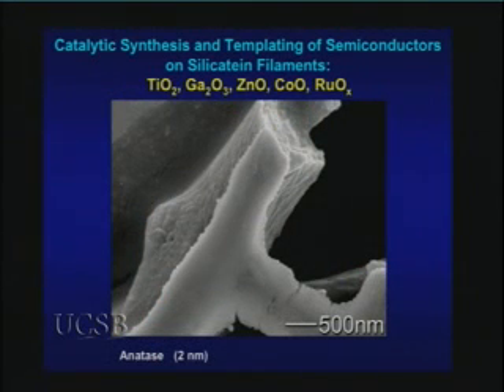Well, realizing that the hydrolysis chemistry was similar to that which can be performed with metals, we realized that the silicon element, a metalloid or metal-like, really would be representative of reactions that this protein could catalyze with a wide range of metal oxide precursors as well. And in fact, we found this is the case. We can use this protein for the catalytic synthesis and templating of a wide range of metal oxide semiconductors. Here you see the protein filament, the thing that looks like a tree in the background, and the newly deposited titanium dioxide, a technologically important metal oxide semiconductor that has grown catalytically from a molecular precursor.